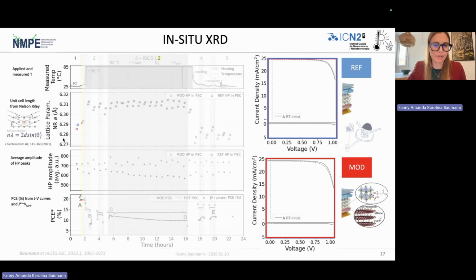So the power out versus the power in, taken from JV curves and compared to the light intensity, which is one sun, approximated to have a similar JV curve as under an AM 1.5G solar simulator. So we're going to go through this step by step. First, at room temperature, we see again, coherently with the previous results, that we have a small compression in the modification, but the JV performance is pretty similar.